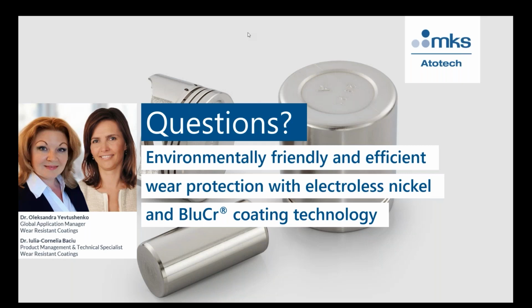I think this is an Electroless nickel question, and I will try to answer it. After the heat treatment, Electroless coating sometimes changes and the deposit shrinks, especially for high phosphorus coatings, because these coatings are amorphous in structure. After heat treatment at about 300 degrees for 4 hours or 400 degrees for 1 hour, the structure changes and nickel phosphide crystallites will appear. This change in structure leads to a shrinkage of the coating volume, and this will induce a high stress in the coating.